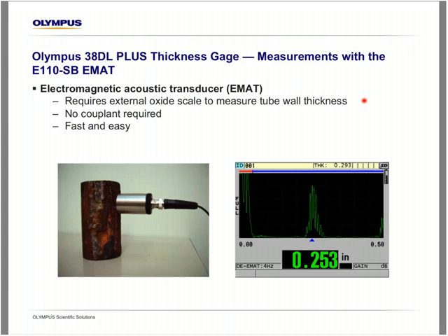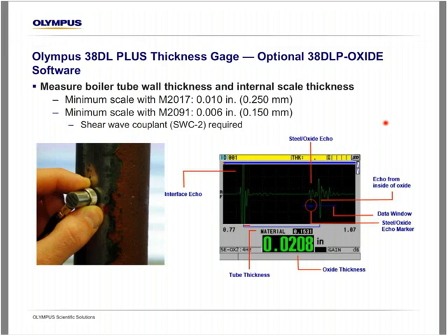So if they determine that the boiler is within spec, they'll remove that external scale and do an internal oxide measurement. The internal oxide scale can actually help protect the steel from corrosion. If the tube maintains a constant temperature, the rate at which that internal oxide scale grows will normally decrease. But if the scale gets too thick, then the insulating properties of that scale are going to cause the temperature of the tube to increase, which then causes that oxide scale to grow quite rapidly. So they definitely want to monitor that scale thickness to make sure that it's not getting too thick.